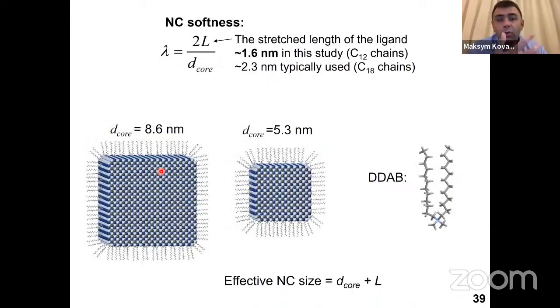And so what we expect is that perovskites actually are soft cubes. Imagine the nanocrystal: it has this very rigid cubic core, and it has these ligands, and ligands are soft. They can bend, they can deform. So there is a certain softness, and the smaller the cube, the greater the softness because the volume occupied by the ligand increases. So to minimize the softness, we actually stick to the shortest ligand which can still provide colloidal stability, which is the one I already showed you in some of the previous slides. And then we took two kinds of cubes. One is the bigger one, which is harder, and the smaller one, which is softer.